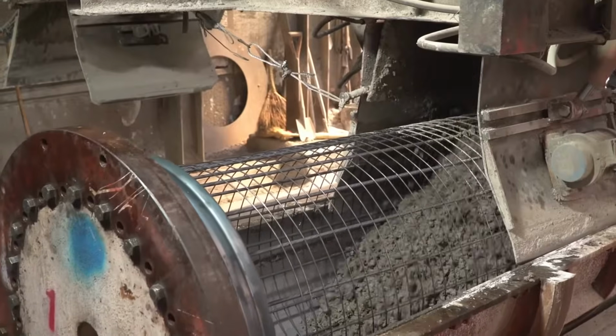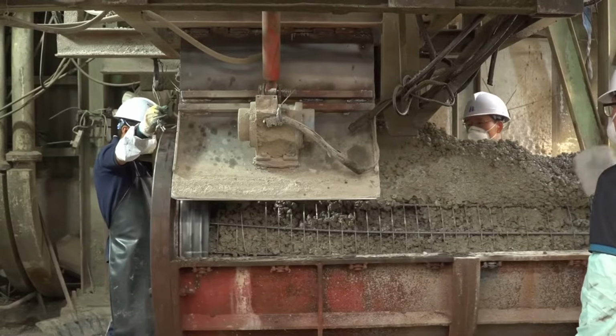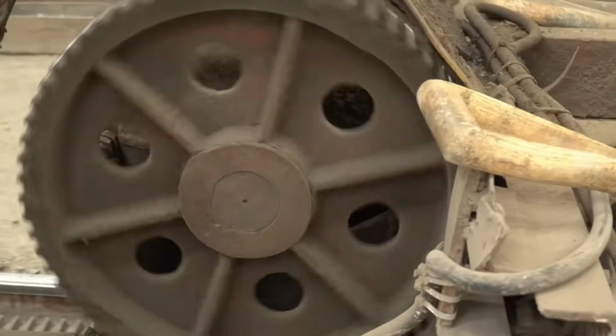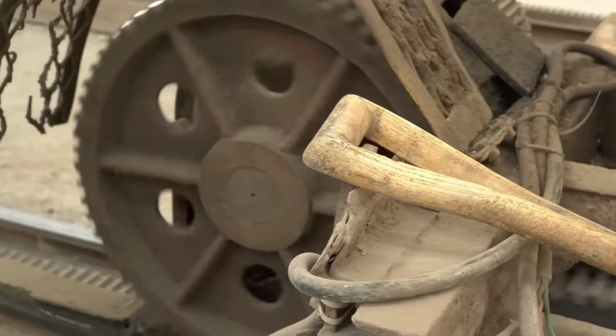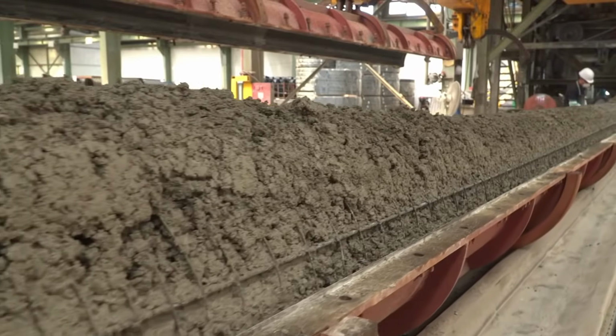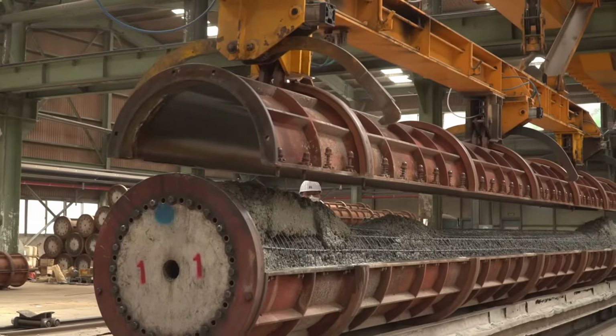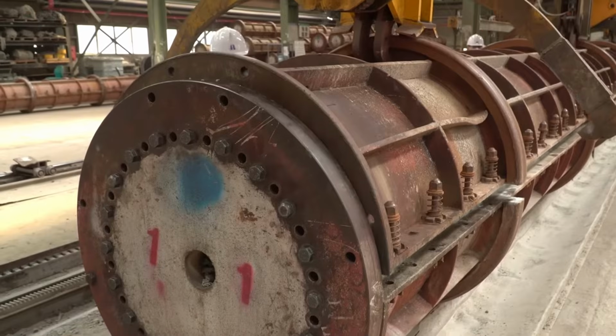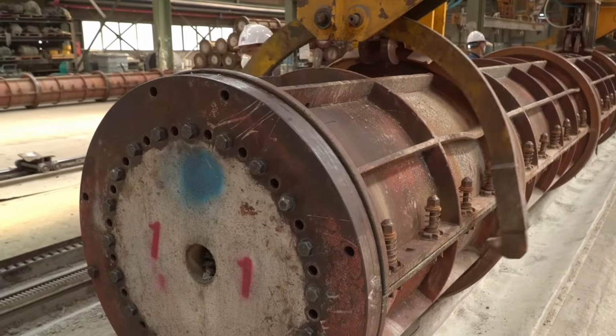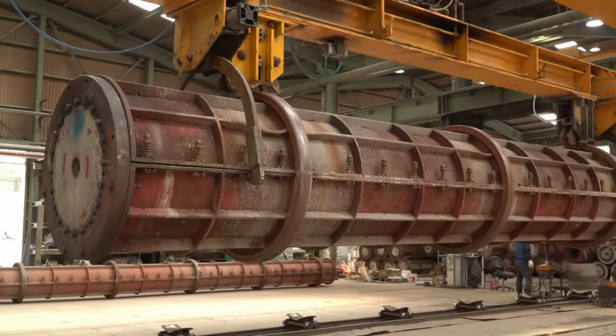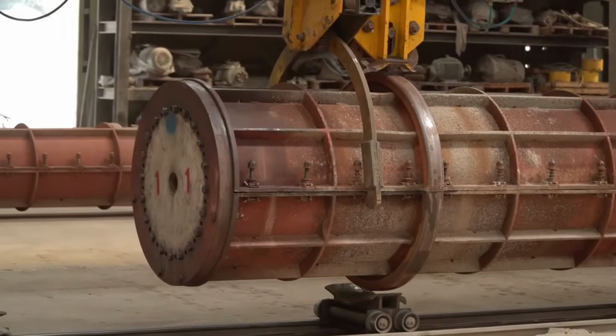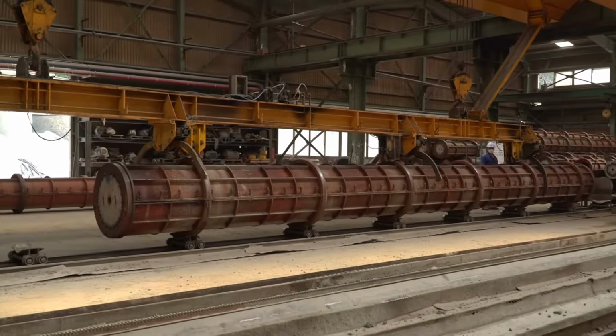The gray slurry flows around the steel cage, filling every gap. Meanwhile, a rotating vibrator runs along the mold, shaking the mixture to release trapped air bubbles and ensure perfect compaction. The goal here: no voids, no weak spots, just smooth, dense concrete wrapped tightly around its steel core.